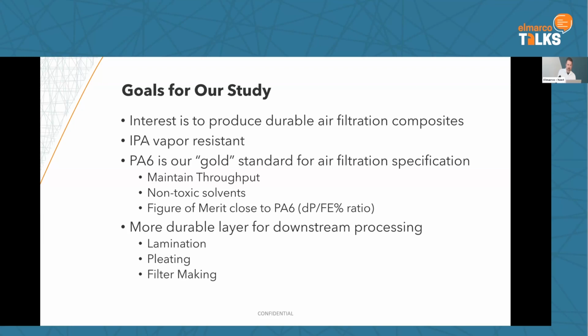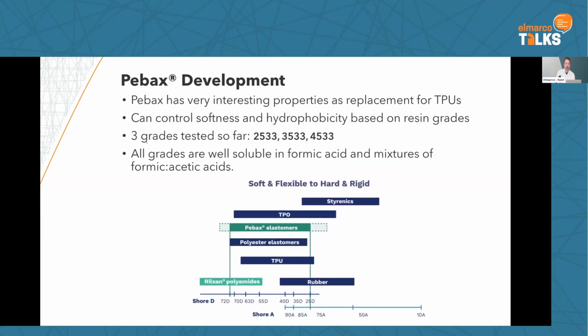So we were in discussion with Arkema about potential materials. We started looking at Pebax as a TPE. We were looking at some TPUs, but they had some drawbacks of not being IPA resistant, or some of the solvents weren't so nice. But we found this really nice material in Pebax that you can control the softness and hydrophobicity, as Stefânia was discussing. And we received 3 grades initially from Arkema, this 2533 up to 4533, and that's just increasing in hardness through those 3 grades. And the good thing about these 3 grades is that we found that they're soluble in formic and acetic acid, which we consider to be more bio-friendly or green solvents, let's say, compared to DMAC, DMF, and those types of solvents.